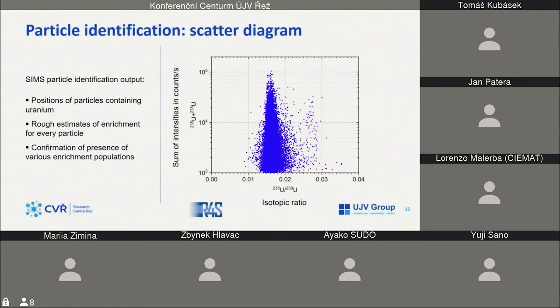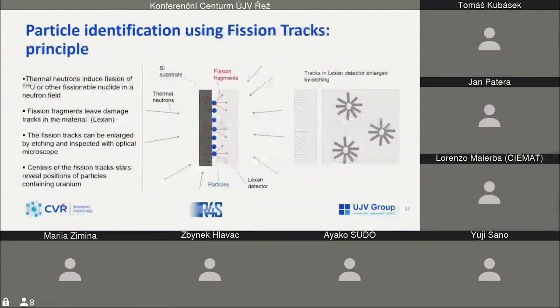In addition to that, we obtain a rough estimate of enrichment for every particle, because we set up the instrument for both uranium-235 and uranium-238. And also from the scatter diagram, which you can see on the right-hand side of the slide, we could identify at least 2 populations of particles. One, a major population, has enrichment around 1.6%, and the second one around 2.6%. So we got very first information which allows us to make a decision on what particle we take for accurate analysis.